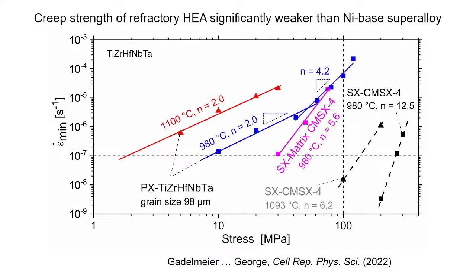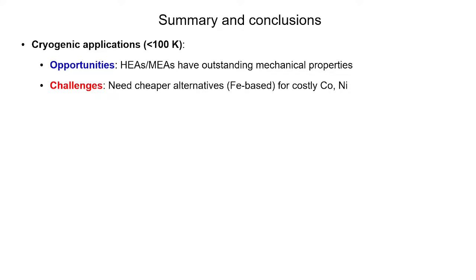And so this is one that many people have been looking at, and we did creep tests on this, and this compares this polycrystalline HEA with CMSX4, which is the state-of-the-art superalloy, and they're orders of magnitude weaker than CMSX4. But what is surprising is that they're also weaker than the single crystal matrix of the superalloy, right? So this is not so surprising because this is a two-phased mixture. But even the matrix, and that's because this is FCC, this is BCC, and diffusion is much faster in the BCC.